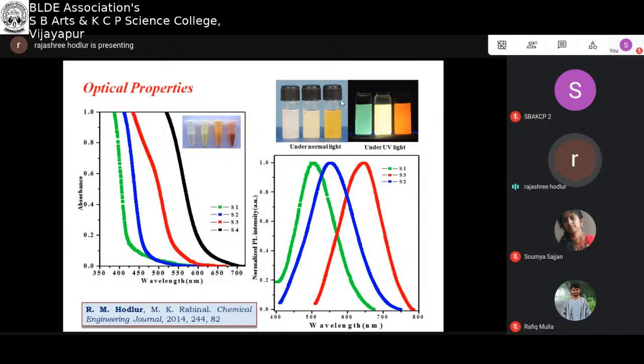So this picture shows how the quantum dots appear under normal light and under UV light. Bulk CdSe appears red to reddish black in color, but we could tune it to different colors. So under normal light, this is how it appears, and under UV light, we observe highly fluorescent quantum dots with very high quantum yield.